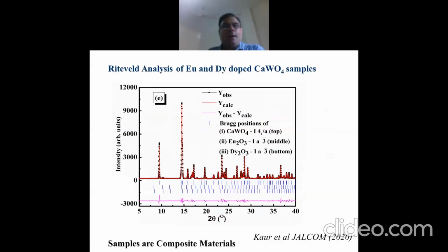We do Rietveld fitting using the FullProf program, and I show you in this picture the peak fitting. We have to incorporate three phases in order to get a good fit of the X-ray diffraction data: the calcium tungstate tetragonal phase, the europium oxide cubic phase, and also the cubic dysprosium oxide phase, to match the refined pattern with the experimentally measured X-ray diffraction pattern. So the samples are composite materials, two-phase or three-phase materials. There is little or no substitution of calcium ions by the rare earth ions.